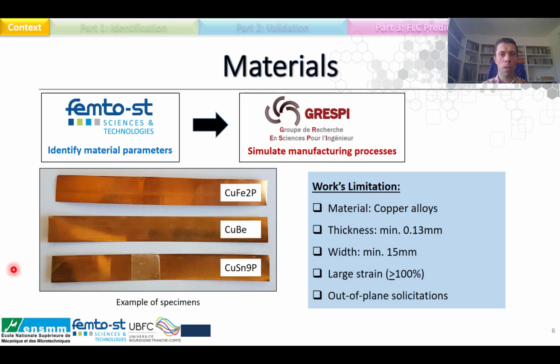So as I said before, our work is to supply the suitable material parameters to GRESPI, and this parameter will be used to realize processes simulation. So we use some experimental tests to identify the material parameters. Within this work, in regards to the material, we have some limitation. So we are working only with copper alloy strips, and so the thickness of these strips is 0.13 millimeters, and they are 15 millimeters width. They will go under a very large strain, and we are having the phenomenon of out-of-plane solicitations.